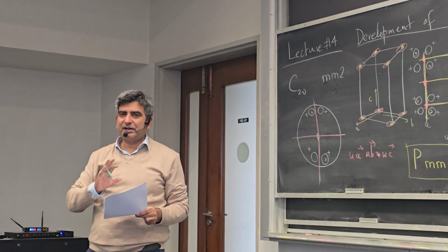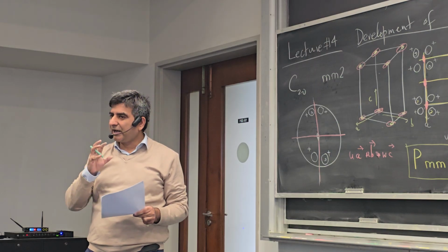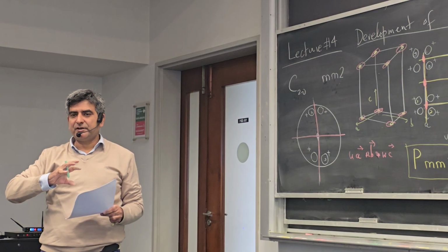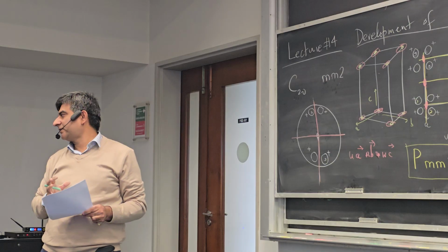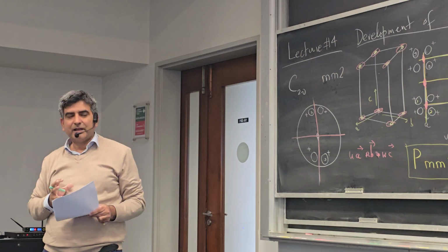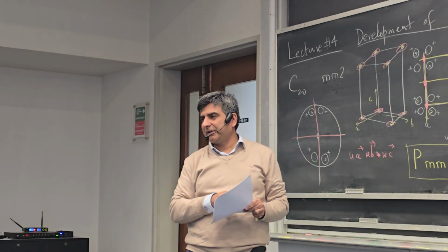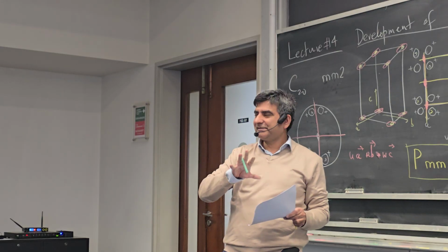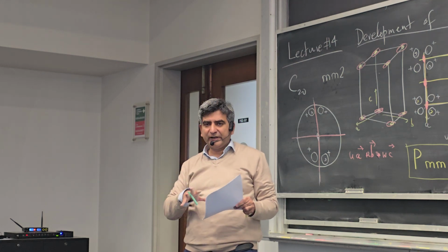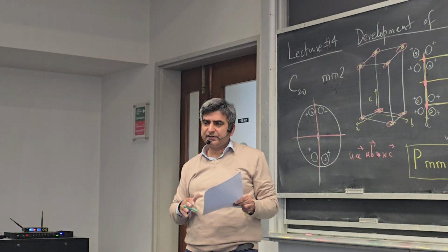So all the symmetry elements are on its outside, so that all the symmetry elements in this space group act on the asymmetric unit to reproduce the entire contents of the unit cell. Okay? So they have defined the asymmetric unit for this space group. Now everything is really, really neat here and very systematic. They have defined the asymmetric unit, the locus for points that form the asymmetric unit. X is less than half, Y is less than half, and Z is anything.